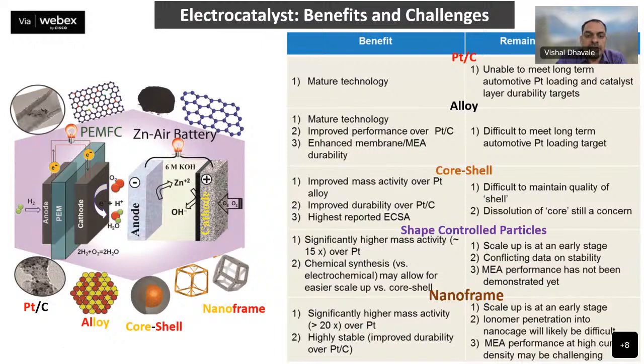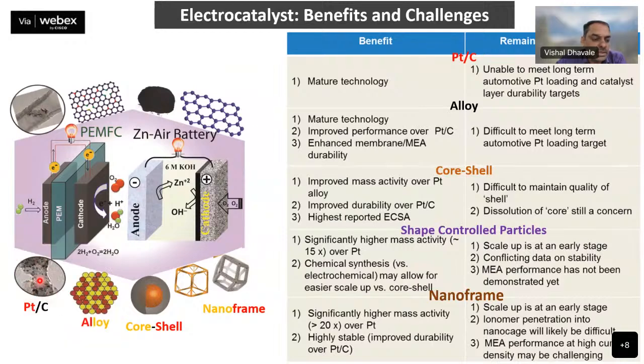If you look into the benefits and challenges of the electrocatalysts so far, on the left-hand side you can start with platinized carbon. You can see the state-of-the-art electrocatalyst is platinum supported on carbon. It has certain problems and challenges listed over here. I'm not going into more detail. From platinum on carbon, people moved to alloy catalysts, where platinum is coupled with a different transition metal to improve the electrochemical activity. But there are certain limitations for alloy catalysts also: despite better catalytic activity, there are leaching problems of the transition metals, and overall stability is a concern.